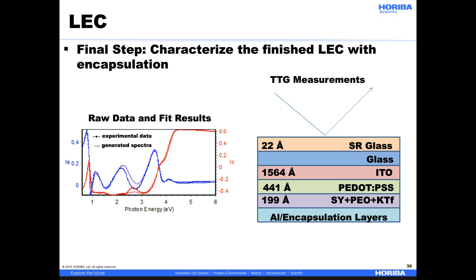So you see the model is flipped. The top layer now is a surface roughness of glass, which we are sensitive to, and we do need to take that into account. Then the glass itself, then the ITO, the PEDOT-PSS, and finally the blend of super yellow plus PEO plus KTF. On the left, you'll see the raw data and the fit results for this entire structure.